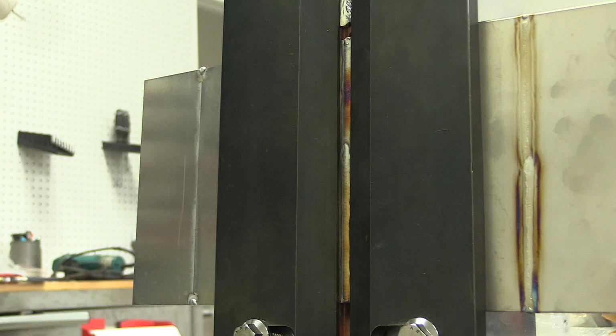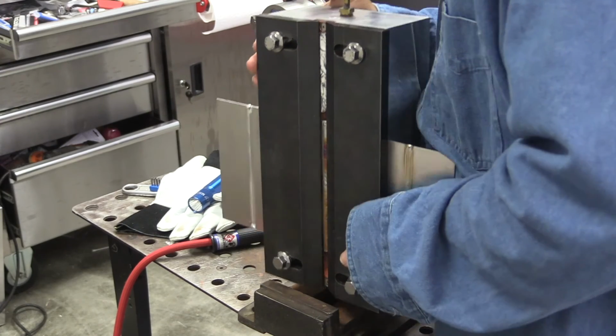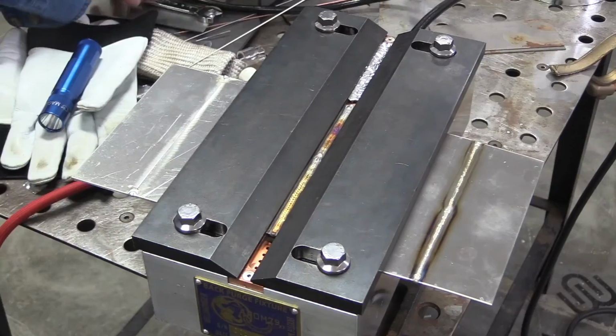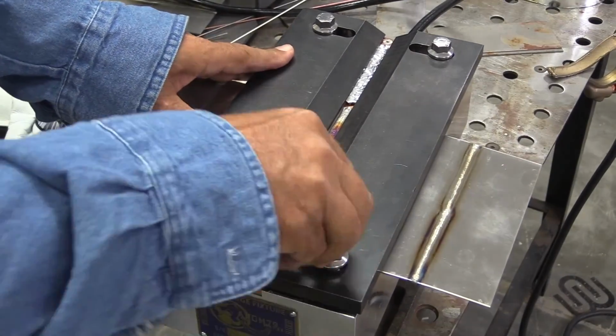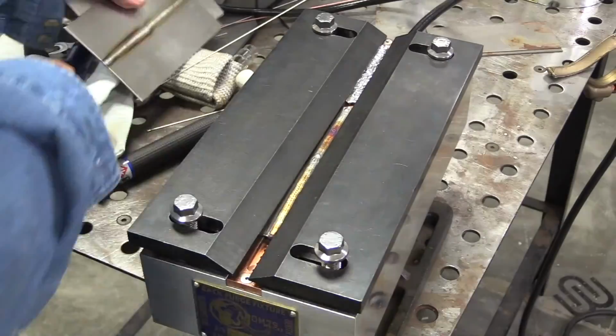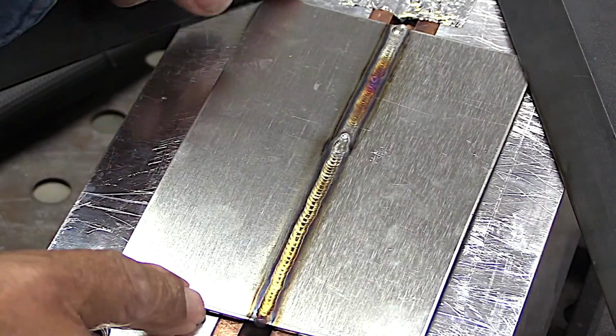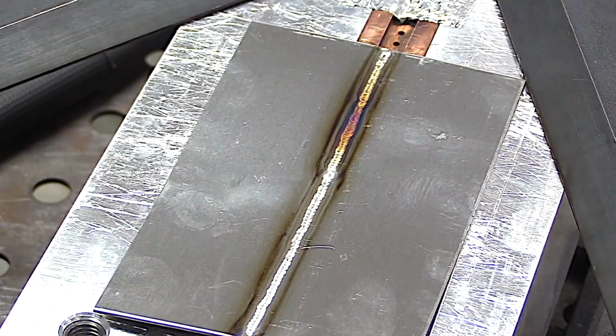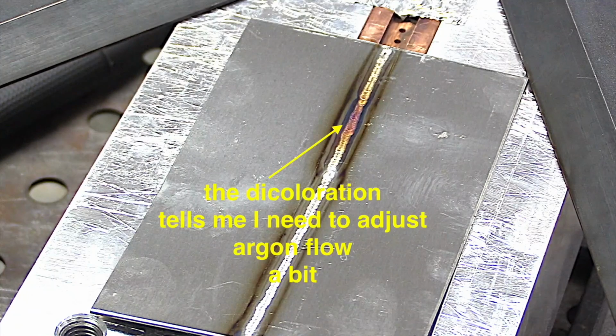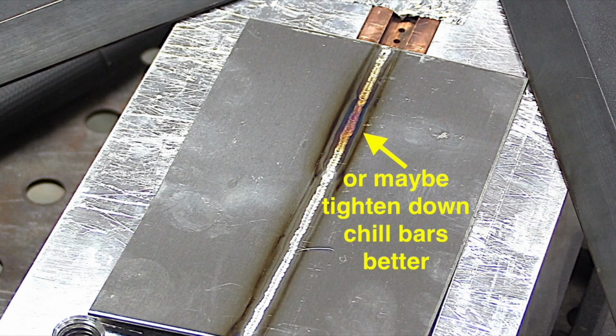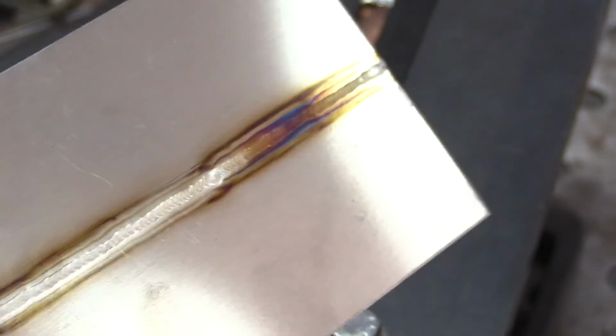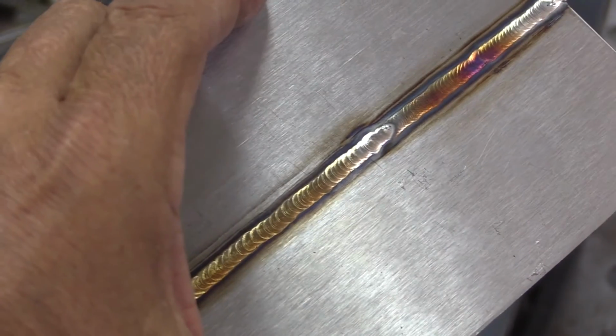Okay, let's pull it out of the fixture, check the backside, see how we did on penetration. Now I'm noticing I got one little spot that discolored more than the rest of it. I think that was because the plates that I used for shim plates were kind of bowed a little bit. See that little spot? That should be white. So I either need to adjust my argon flow on the fixture or possibly just get a better mate on the chill bars. I'm pretty sure it was just the chill bars actually.